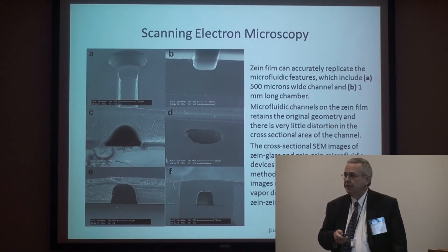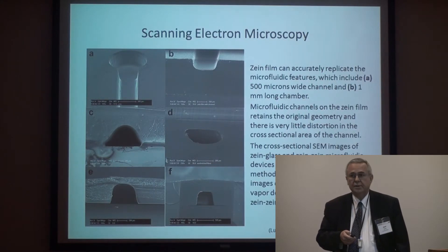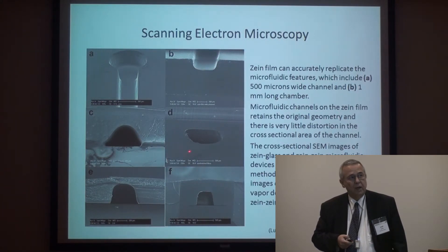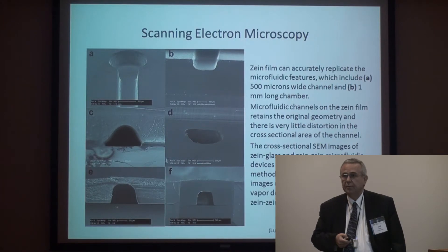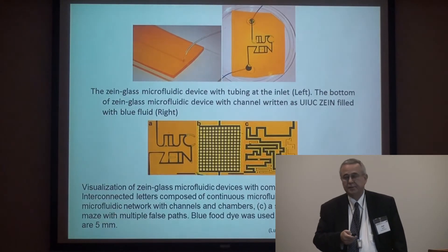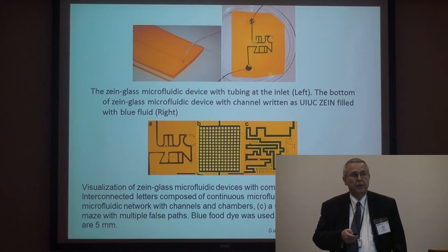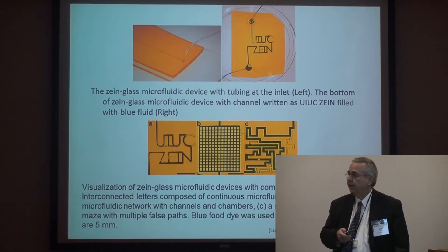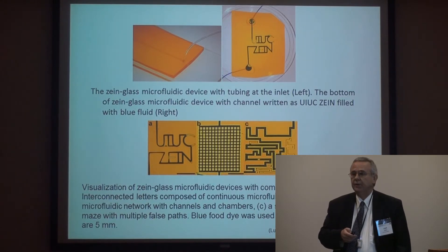We have considered Zein-to-Zein seals, and the seal was created essentially by vapor deposition of ethanol. When you take a scanning electron micrograph of a vapor-deposited Zein-to-Zein surface, there is a complete fusion of one Zein layer onto the other. We have also looked at Zein-to-Glass microfluidic devices. We are collaborating with Nano-Ink to come up with surface etching using ethanol so that we have a completely biodegradable process and do not utilize PDMS to form these particular channels.